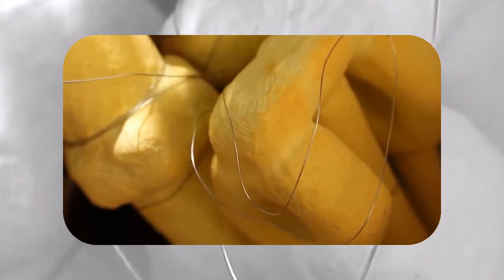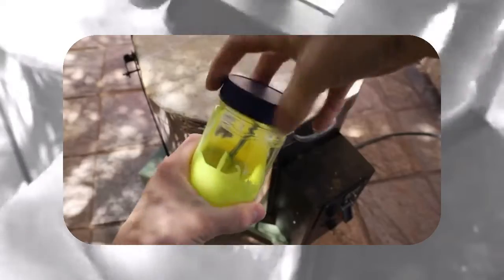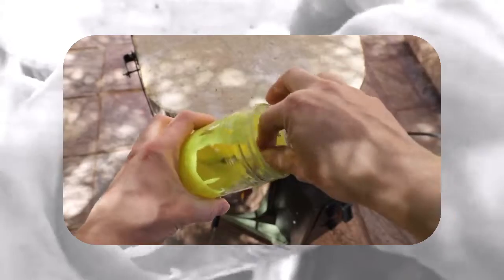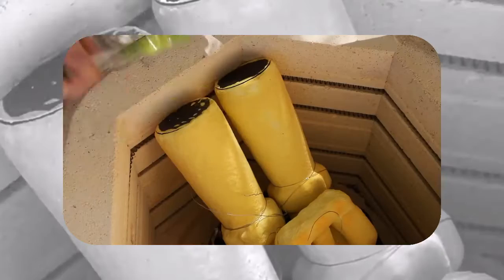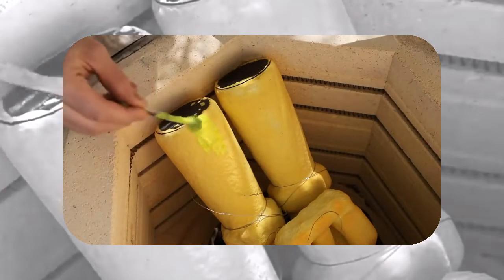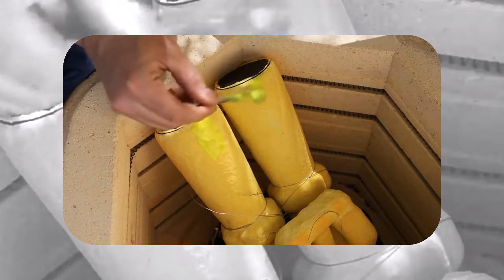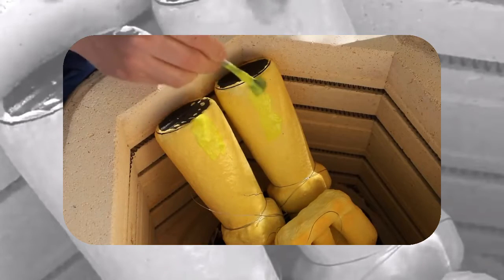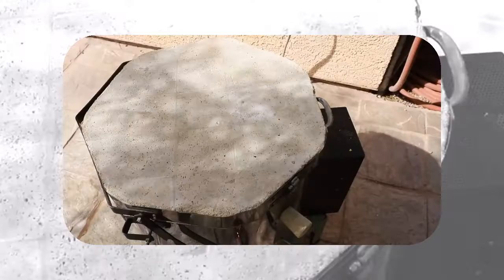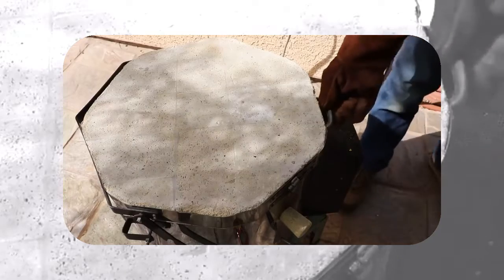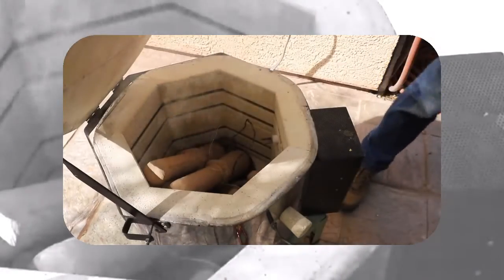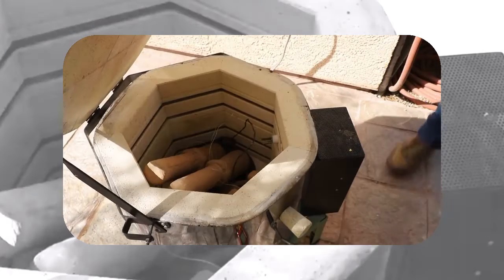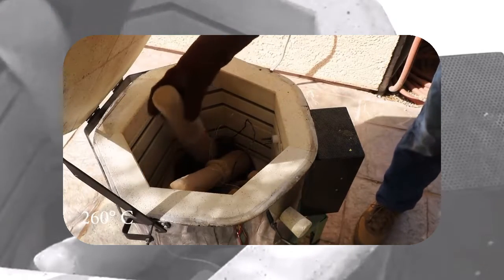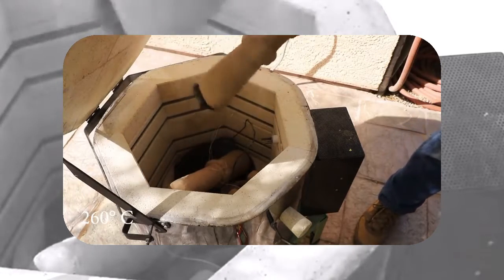As usual, the ceramic shells cracked in a few places as soon as the temperature rose to a couple hundred degrees Fahrenheit. This actually isn't a big deal. I've figured out that a great way to seal the cracks is to brush on some slurry while the shells are still relatively hot. This way, the slurry dries almost instantly, allowing me to quickly build up thick patches. Once the cracks were fixed, I placed the shells back into the kiln and heated them up to about 500 degrees Fahrenheit, which is the temperature at which the PLA starts to melt out of the shells.